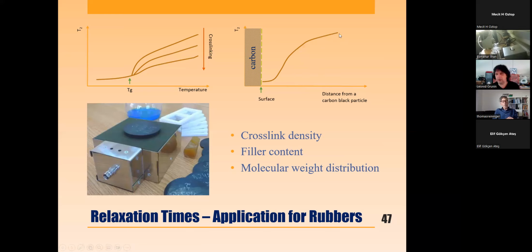Also, you can observe the so-called interface effect. So this is a model of distance from the particle of carbon black that adsorbs the molecular chains, and whilst they are attached to the particle, they have low mobility and lower T2, and further away they have high T2. So by applying time domain NMR, you can measure cross-link density, or you can measure filler content, and you can measure molecular weight distribution.